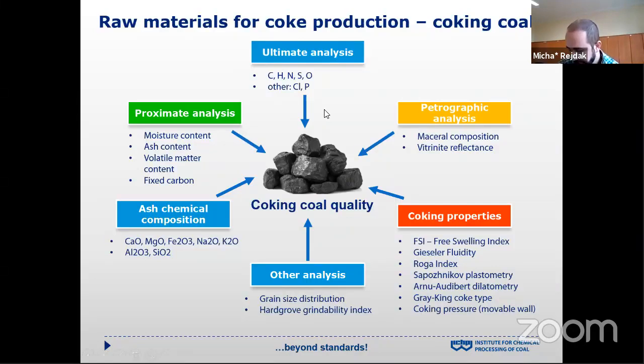Many parameters, as you can see, can be evaluated to assess the suitability of coal for the coking process. And of course, based on the knowledge of these parameters, recipes of coke blend are established. The most popular, commonly assessed parameters are, of course, the parameters of proximate analysis. I mean moisture content, ash content, volatile matter content, fixed carbon, and the ash chemical composition, the composition of oxides in the ash, because some oxides can act as the catalyst of the carbon dioxide reaction, gasification of coke.